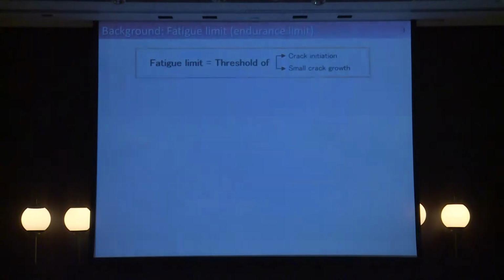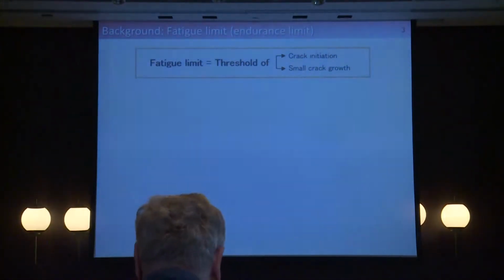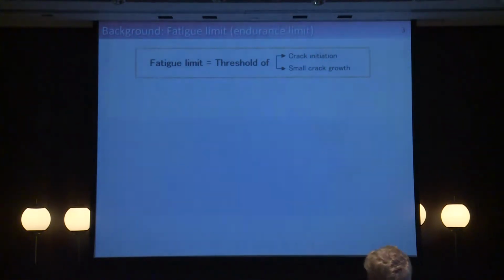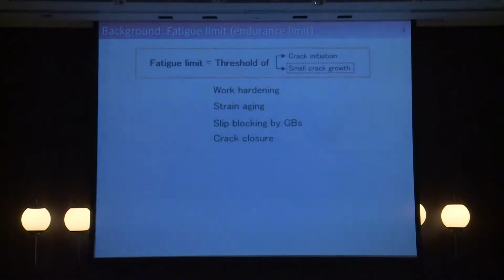So let me explain our strategy towards such a goal. From a microscopic viewpoint, fatigue limit has been found to be the threshold against either of two phenomena. That is, initiation of a small crack or the arrest of a small crack. In the case of conventional steels, it has been found that the fatigue limit corresponds to the threshold of small fatigue crack growth. And why is a crack in a steel easily arrested? There are several mechanisms. For example, work hardening or strain aging near the crack tip, or slip blocking by grain boundaries, or a crack closure phenomenon. What we focused on here is strain aging.